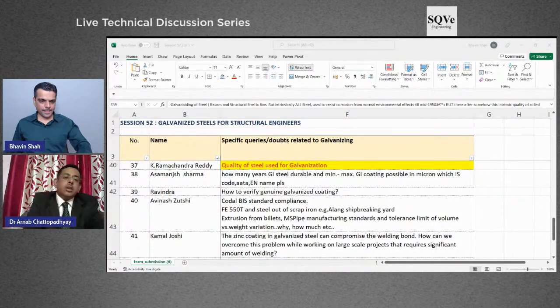There are limitations for steels in the continuous galvanizing process, because there are some high strength automobile steels which cannot be continuously galvanized properly. But in batch galvanizing, most steels can be galvanized. There are some problems with silicon steels, because silicon reacts with the zinc, which is called the Sandelin effect, and causes problems for the galvanized surface. But those also can be handled. So most steels, even high silicon steels, can be galvanized. It is your requirement to determine what sort of steels you are using. All at the end can be galvanized.